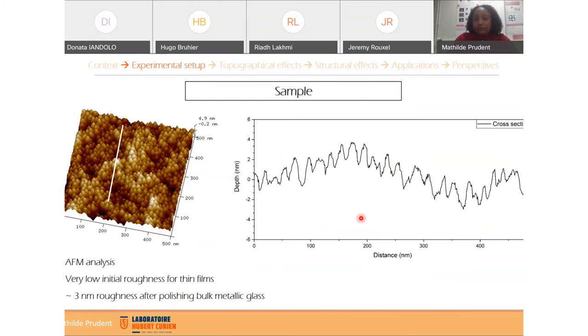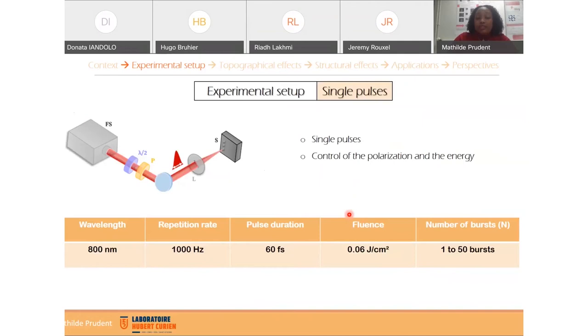So to irradiate these thin film metallic glasses, we just use a direct setup that allows us to create single pulses. In this setup, we have a half-wave plate and also a polarizer that allow us to control perfectly the polarization and also the energy. We used for that a laser with a wavelength of 800 nanometers, a repetition rate of 1 kilohertz, and we fixed the pulse duration to 60 femtoseconds. We used for the test a fluence of 0.06 joules per centimeter square. And we just varied the number of pulses between 1 and 50.